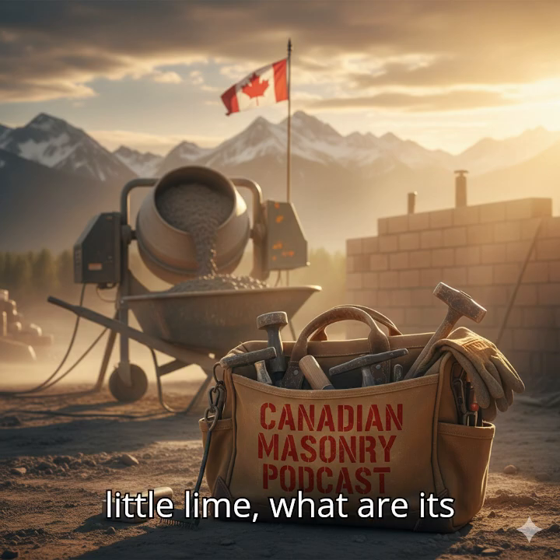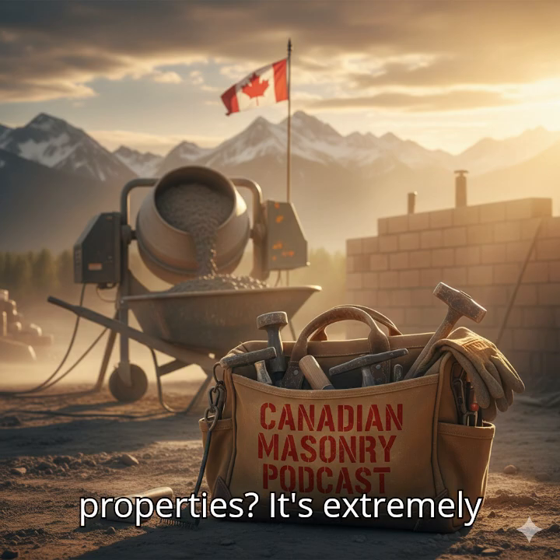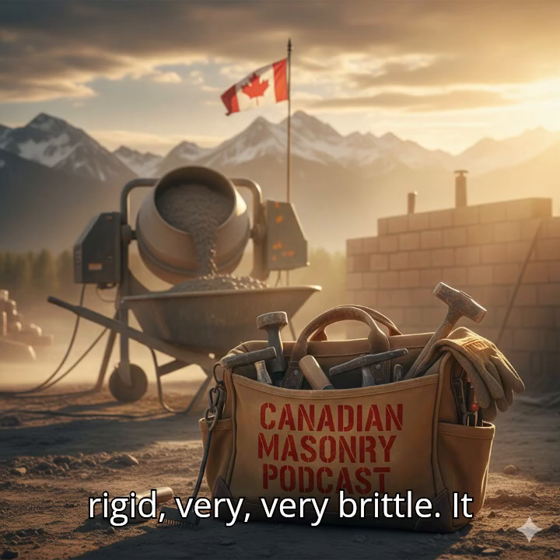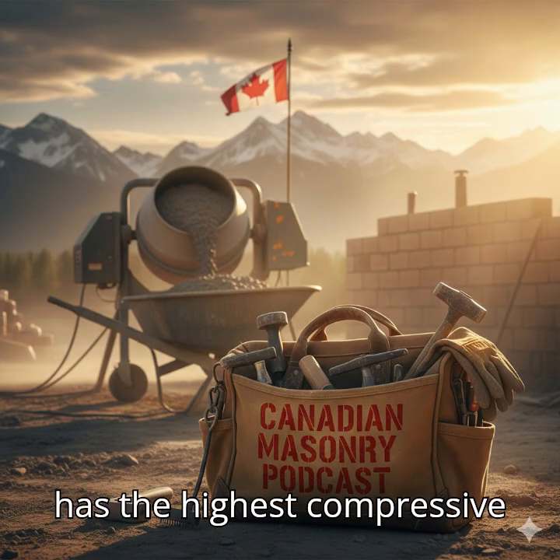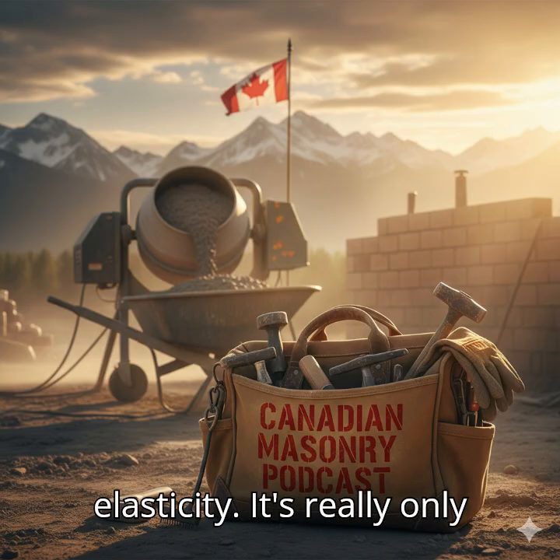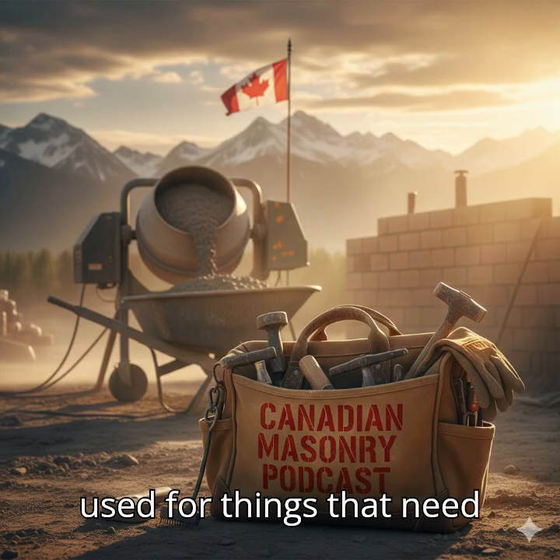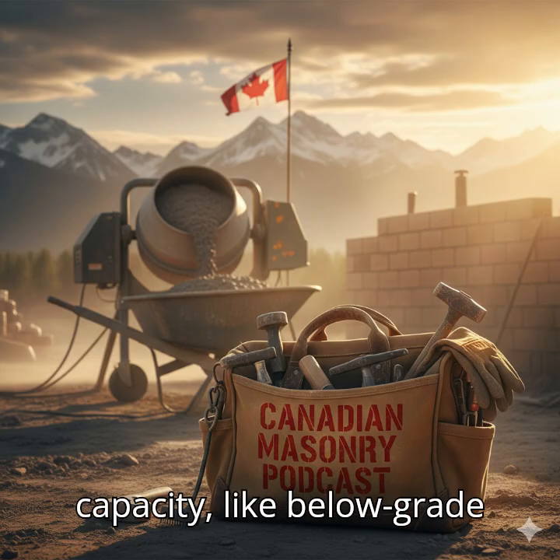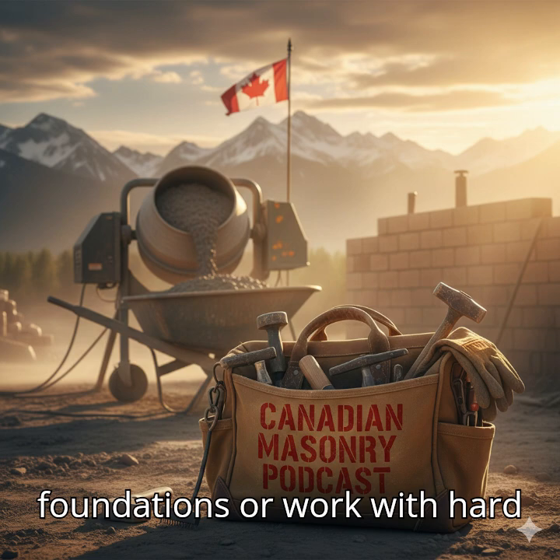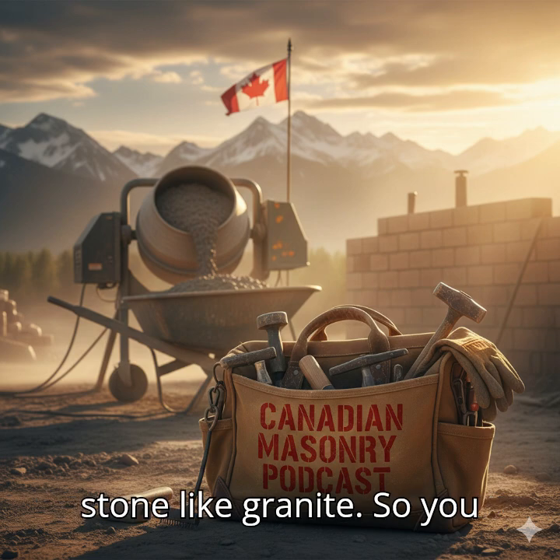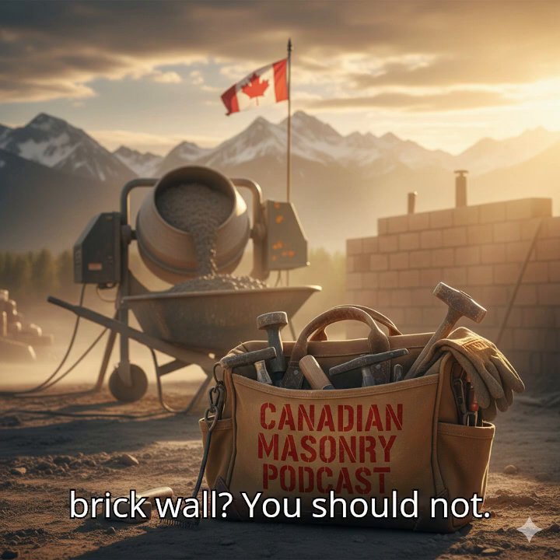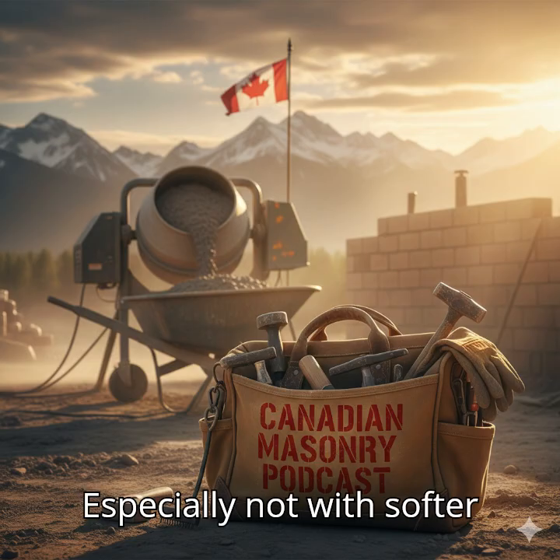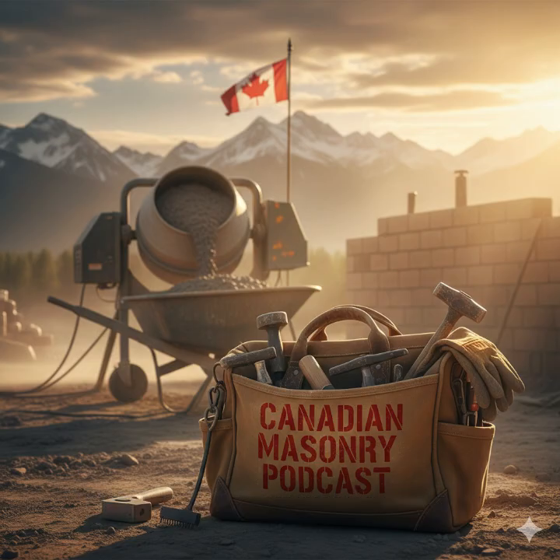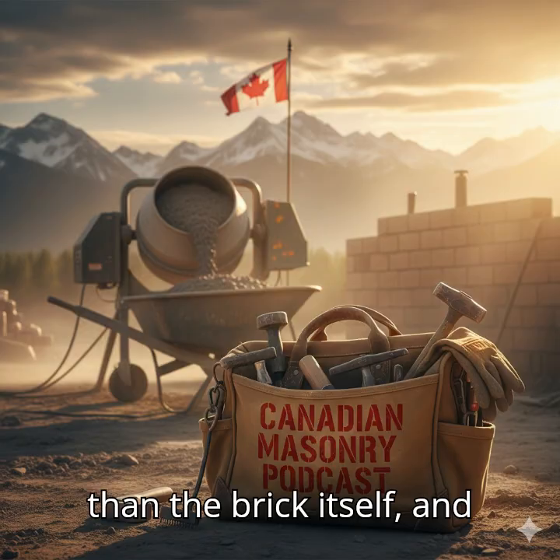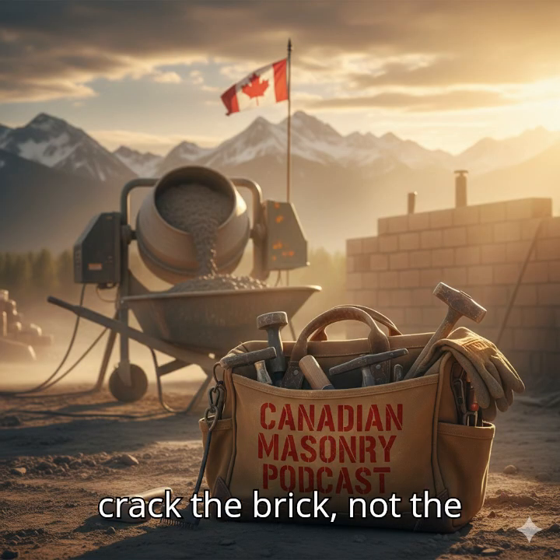So with that little lime, what are its properties? It's extremely rigid, very, very brittle. It has the highest compressive strength, but minimal elasticity. It's really only used for things that need maximum load-bearing capacity, like below-grade foundations or work with hard stone like granite. So you wouldn't use it on a regular brick wall? You should not, especially not with softer units like concrete brick. The mortar would be stronger than the brick itself, and any movement would actually crack the brick, not the joint.